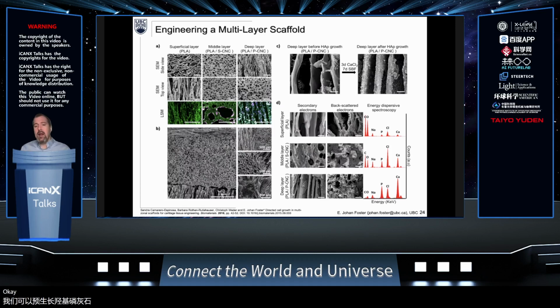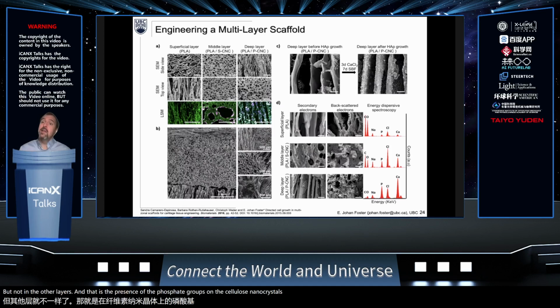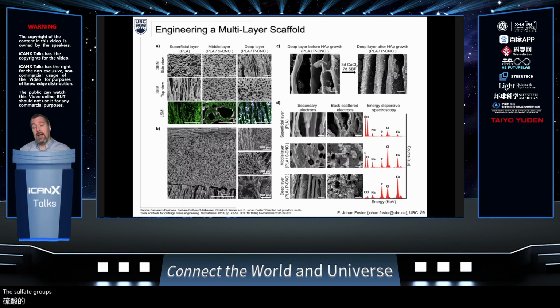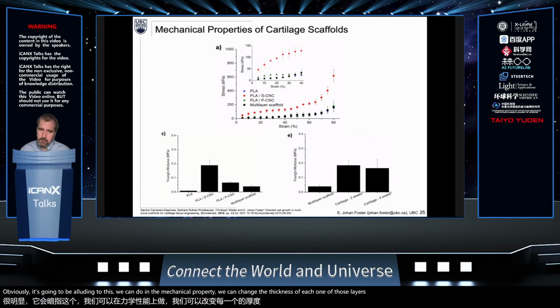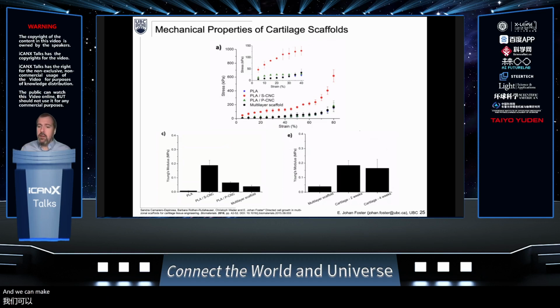Okay, in the bottom right, we show that we can grow hydroxyapatite in the deep zone, but not in the other layers, and that is the presence of the phosphate groups on the cellulose nanocrystals. The sulfate groups or just hydroxyl groups on the surface do not cause hydroxyapatite growth. Okay. So one very interesting thing, obviously I've been alluding to this, we can tune the mechanical properties. We can change the thickness of each one of those layers. And we can make multi-layer scaffolds.